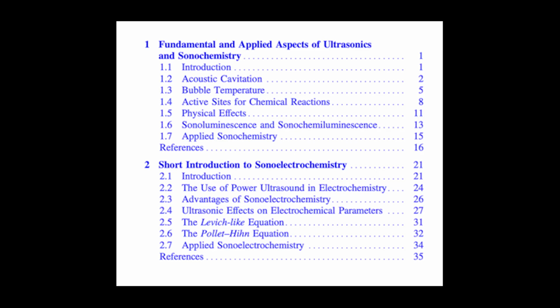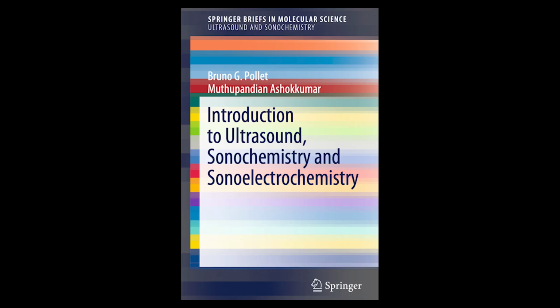And maybe even more importantly for reactor design, the limiting current is inversely proportional to the square root of the distance between the ultrasonic horn and the electrode surface. So bringing the horn closer has a big impact. A very big impact. Halving the distance increases the limiting current by about 40%, same as doubling the power. This gives engineers direct levers to pull, power and distance, to control the mass transport intensity in their reactor design.